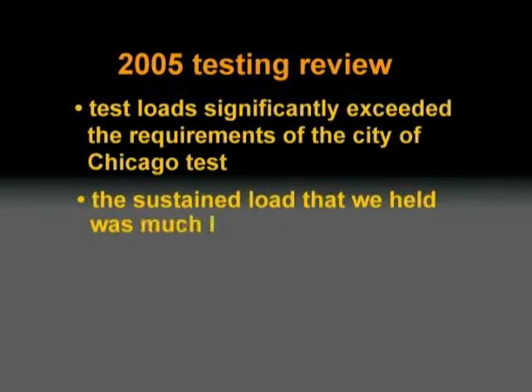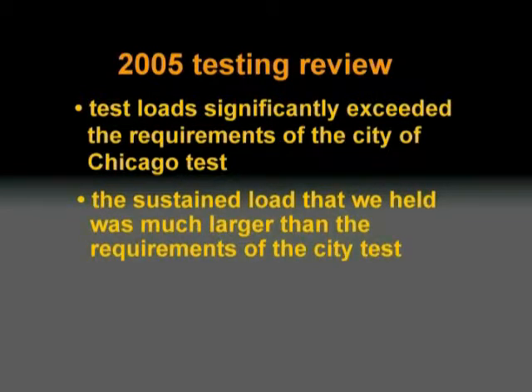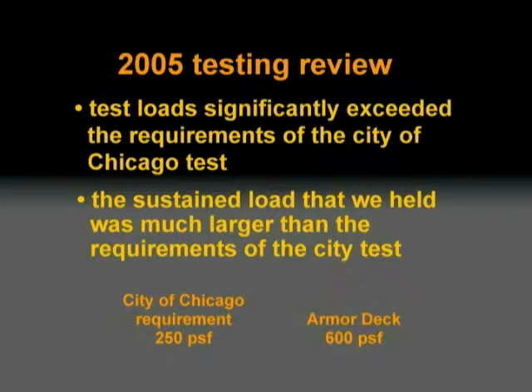And the sustained load that we held was much larger than the requirements of the city test, which would have been 250 PSF. We held a load of 600 PSF, but we only held that load for 12 hours, where the City of Chicago required that the load be held for 24 hours. Because our test protocol didn't exactly match the city test protocol, they required that we do design calculations, or load capacity calculations for this panel.